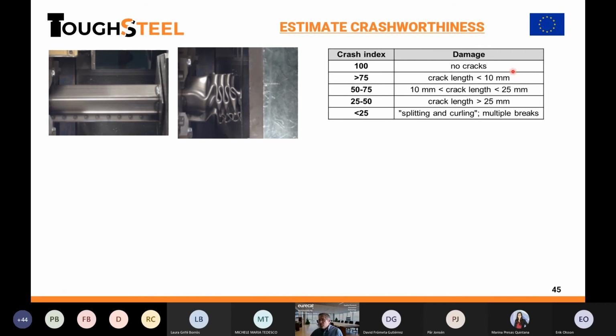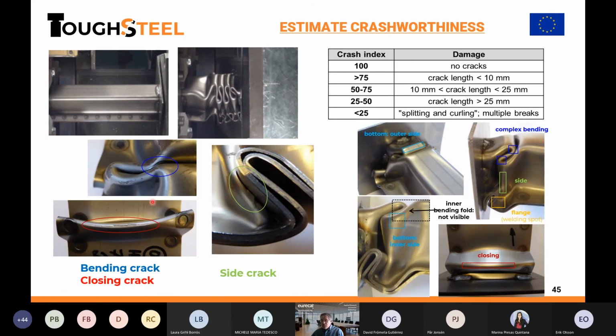This is how usually automotive is indexing the crash resistance, by the number of cracks. This is the beam or the specimen that is before crashing, and this is after crashing. You see the folds here, and counting the cracks that appear at the folds, at the side, or at the different parts, counting these cracks. If the material has no cracks, high crash index. If the material is destroyed, low crash index. And in the middle, depending on the crack length and position, this crash index is different.